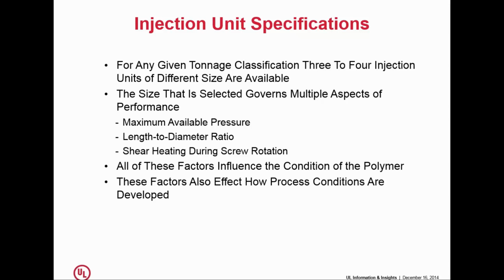So keep in mind that if you set 75 RPMs, which is a lot of times how we're looking at screw settings, and you have a 1-inch diameter screw, that's a different rate of travel around the circle than it is if it's a 2-inch diameter or a 3-inch diameter screw. So these are actual plastic conditions that we very often do not look at. We tend to look at machine conditions. And all these factors influence the condition of the polymer. And these factors will also affect how you develop your process conditions.